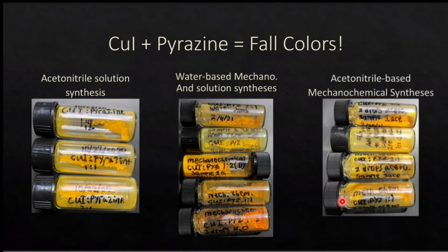And so then we moved on to see if the same thing would happen with acetonitrile, or whether it would be as consistent as the solution synthesis pathway. And what we found is there's a little bit more variability, but generally it was much more consistent than the water-based mechanochemical. And so we were like, what's happening here? So then during that process, we found something kind of interesting.